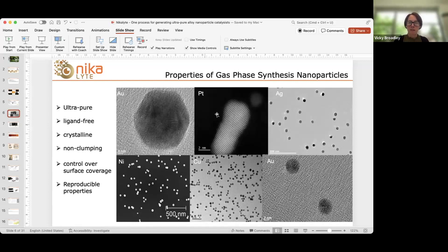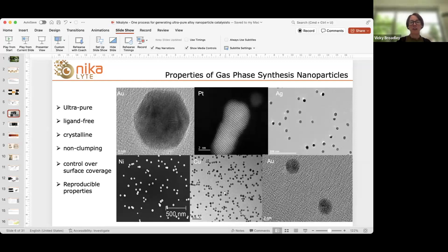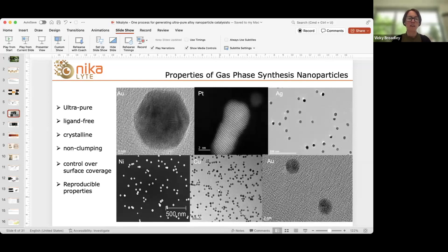Now I'll show some images of typical nanoparticles generated in our equipment. The key property is that they are ultra-pure. You start with a very pure target, use very pure process gases, and then you have your substrate. That's it — no chemicals, no precursors, no other solutions needed. So when you generate nanoparticles of gold, platinum, or silver, you end up with just pure gold, platinum, and silver on your surface — no ligands or precursors left over. These materials are also crystalline — you can see the crystal lattice and individual atoms.